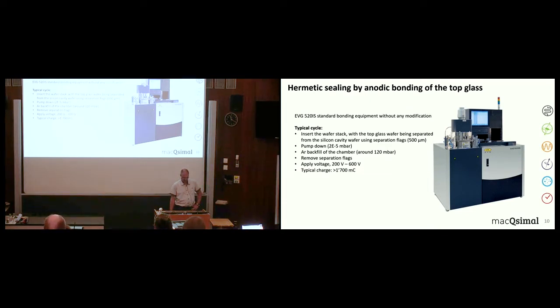Then once we reach the required vacuum level, we make a backfill with argon gas in the chamber, about 120 millibar. Then we remove the separation flags, so the glass wafer and the silicon wafer get in intimate contact, and we apply a voltage which we vary during the process from 200 to 600 volt to induce the anodic bonding. And typically we achieve a charge of more than 1,700 millicoulomb, which indicates a good quality bond.